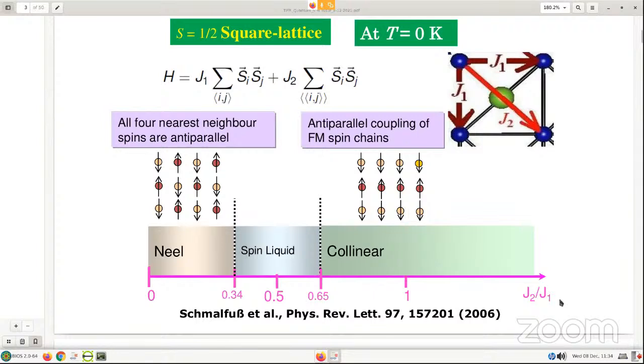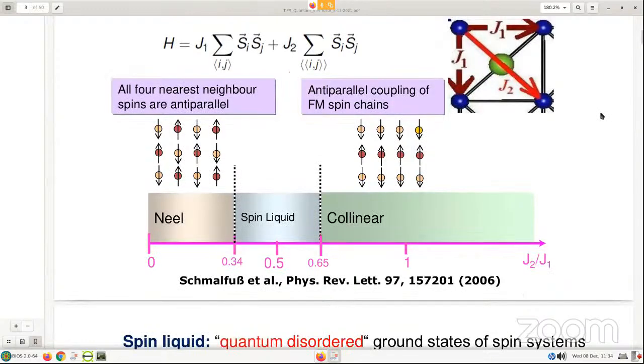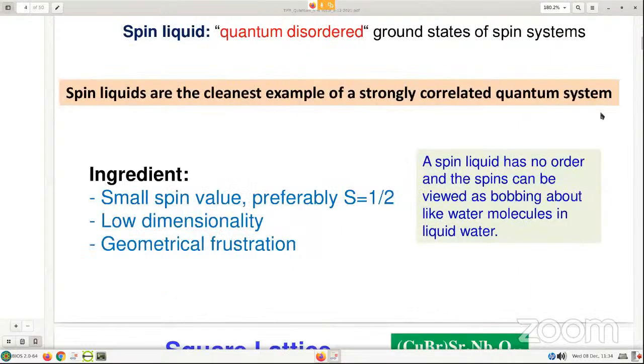But when J2 by J1 is about 0.5, then you see the quantum phase, that is the spin liquid phase. And if we go to higher strength of J2, of course, it comes back to the collinear antiferromagnetic structure. So this is the relative strength of these 2 exchange interactions. In the case of a square lattice, it really matters what kind of magnetic phase you are going to see. And the quantum spin